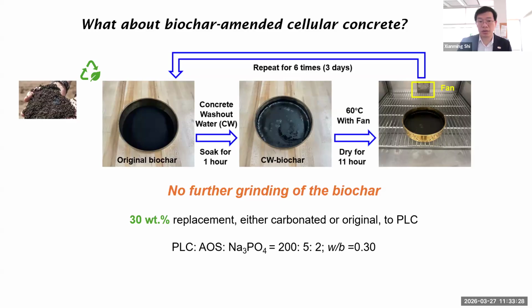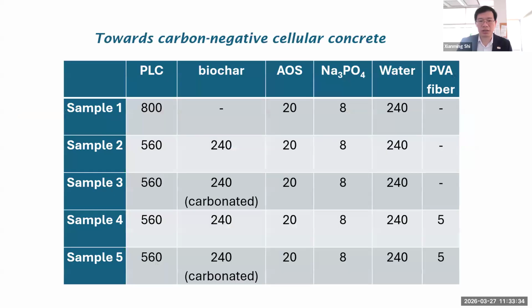So here we aim for 30% replacement of cement by biochar. And we had a few mixed designs. The AOS is basically a foaming agent working in combination with sodium phosphate. They seem to foam and stabilize the foam inside the cellular concrete.